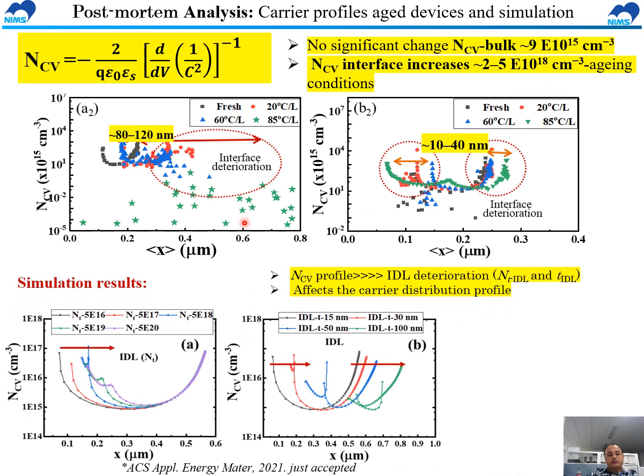And then we also reproduced those characteristics with simulation using SCAPS, and we varied the interfacial defect layer density and interfacial defect layer thickness. It follows those trends, and somehow it explains our result that widening of the interfacial defective layer is one of the causes for the device deterioration.